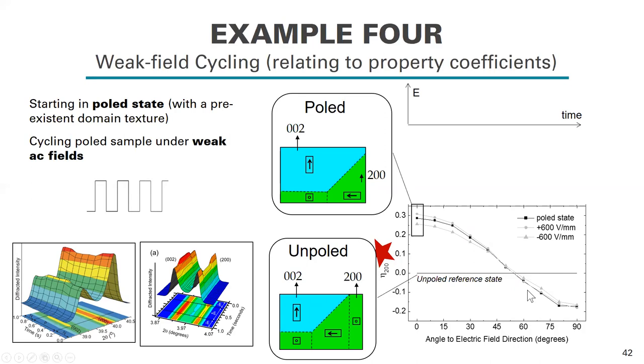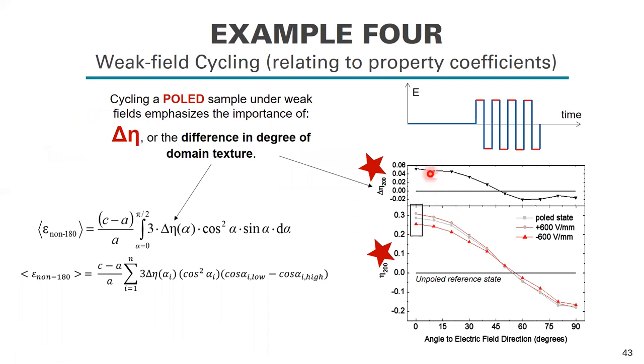And when we're at the poled state, we're gonna cycle it under these weak electric fields. So I'm gonna represent that here on the top right figure as electric field versus time, and then animate this down here to show you as you apply a positive and negative state to your poled sample, you're actually generating a change in the texture. Okay. Now we represent that on this top plot as delta eta. Okay. So again, poling takes you from unpoled to the gray line, and then cycling it allows you to go between these two states. Okay? The difference between those two states is the strain that you want. So that value is important. And now if we do this strain calculation for the deltas between the positive and negative states, we can calculate the contribution to strain under weak field conditions.